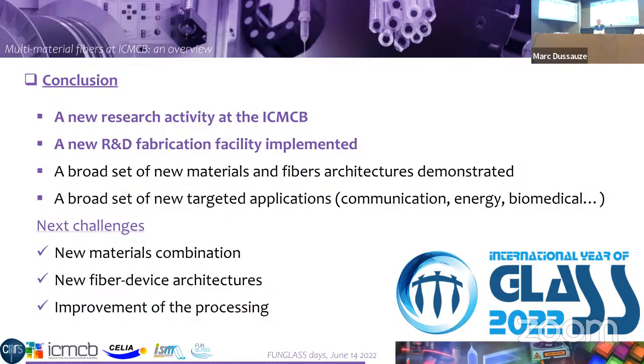So we demonstrated that we can bring new materials into these fibers, a lot of types of glasses with many applications, especially many glasses transparent into the infrared up to some 5-6 microns, which is very useful for sensing, for instance. And then we are targeting many applications. And just to finish, the new challenge is, of course, having more materials, new shapes, and then improving the overall processing of the method, including, of course, lowering the losses. I think this is it.